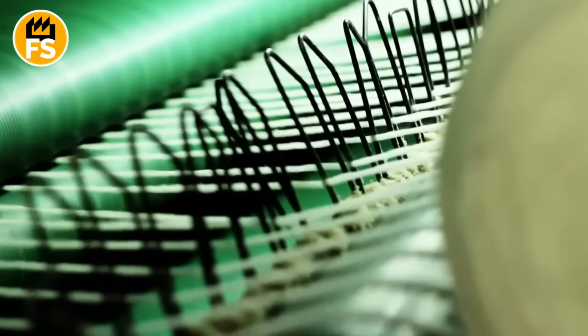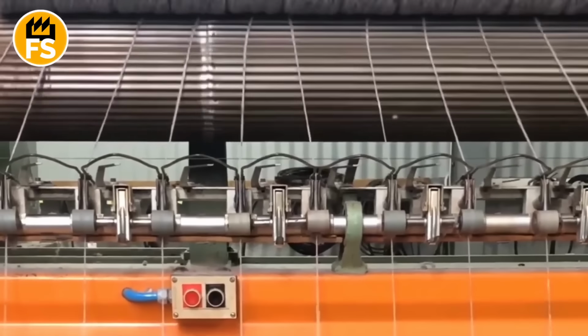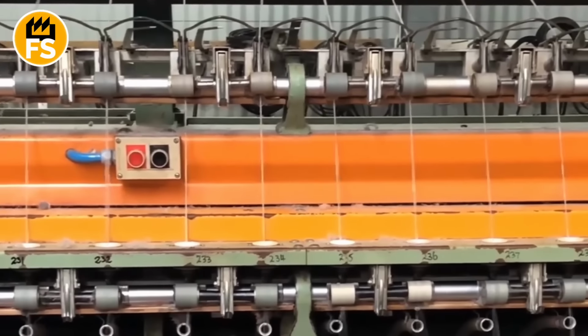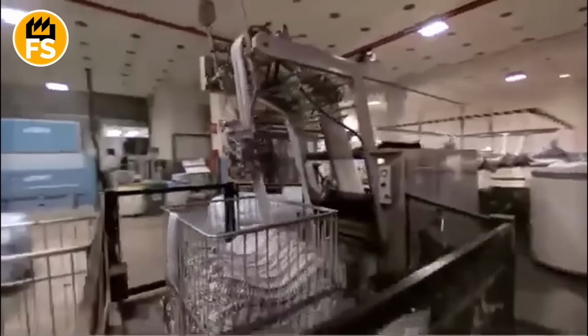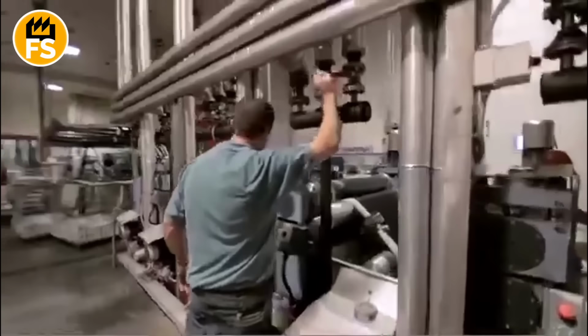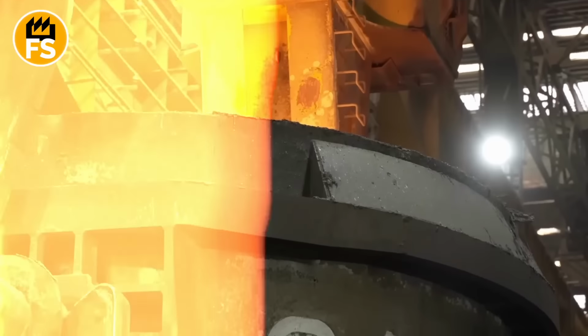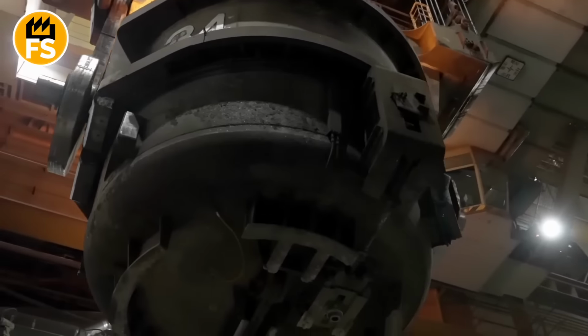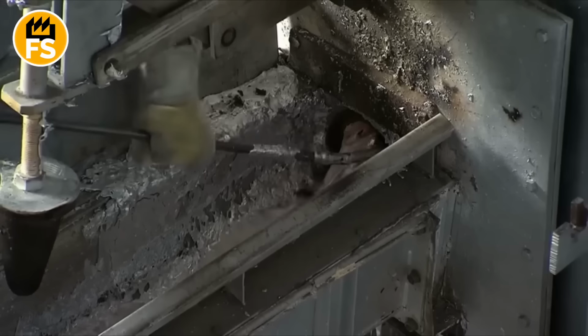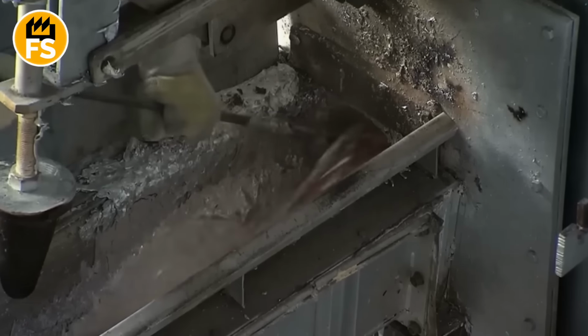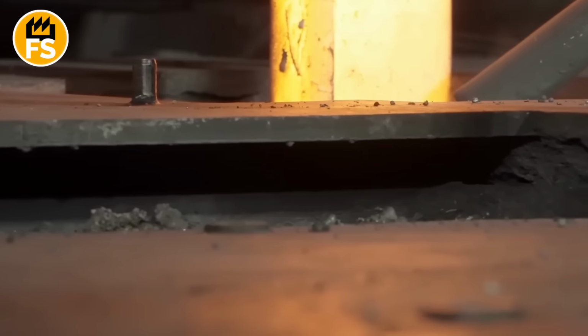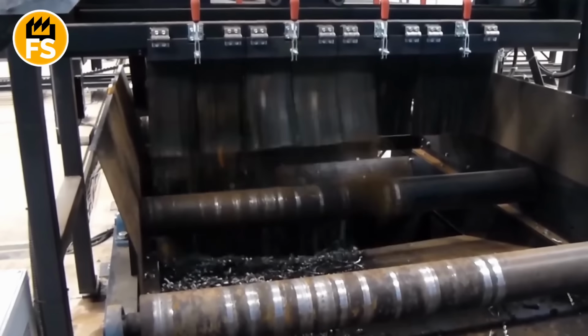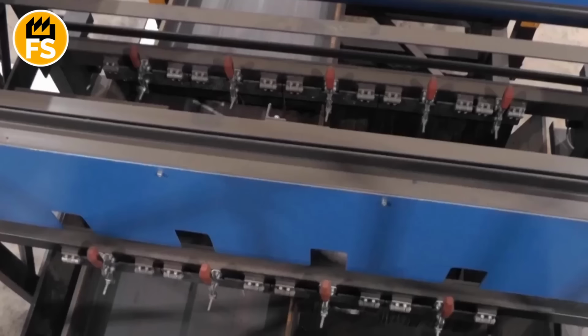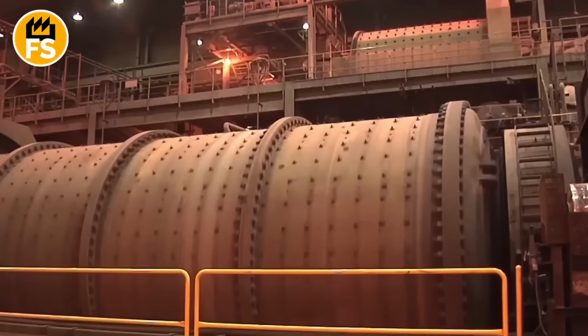To the touch, after several passes, the wire becomes thinner and longer, like a silvery strand of hair. The surface is smooth, cool, with a clear metallic sheen. Importantly, this entire process happens without heating. The metal remains cold. That's why it's called cold drawing. The steel gets stronger in the process. Its structure becomes denser and more durable, like a muscle that's been trained. And so, ring after ring, an ordinary wire rod transforms into a high-precision wire for a future steel cable.